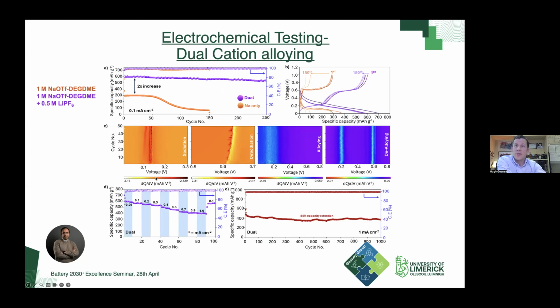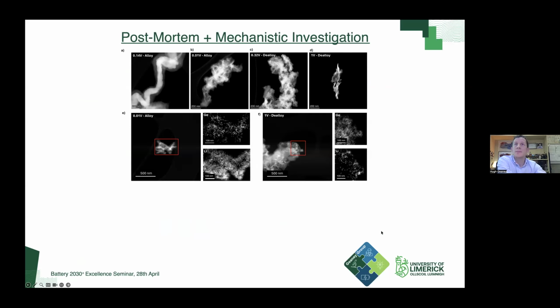We did standard rate capability just because every reviewer wants to see these in battery papers, but also showed, much more importantly, that this is reversible up to 1,000 cycles.